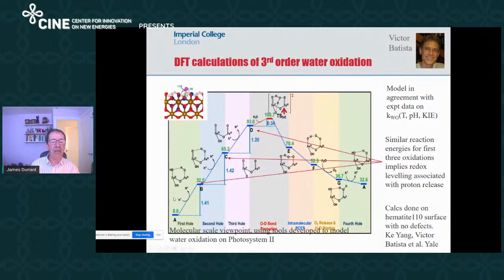But the point is that what he was able to show was that the surface of hematite can enable three holes to come together in three different oxidations, where each oxidation step is essentially at the same potential. So this is the redox leveling, which, for example, we see in the manganese cluster of PS2, to achieve the three holes coming together, and then the final reaction to drive the water oxidation is at a rather small activation barrier, which is consistent with our data. And indeed, this sort of model fits not just our temperature dependence, but our pH dependence, and when we do kinetic isotope effect labeling measurements on the rate constant.